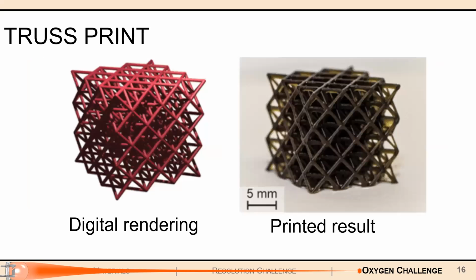We can also make some additional, more complex prints with this, such as this truss right here, where we can see that our digital rendering to the left and also the printed results to the right look pretty close to each other. That's very good. We want this high resolution, and that's going to be good for future prints. However, it's not going to be that simple because of the fact that, again, this requires inert gas. And I'm presuming that most of you don't have, say, a tank of argon lying around somewhere in your garage.